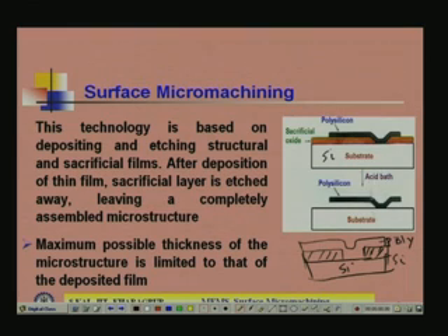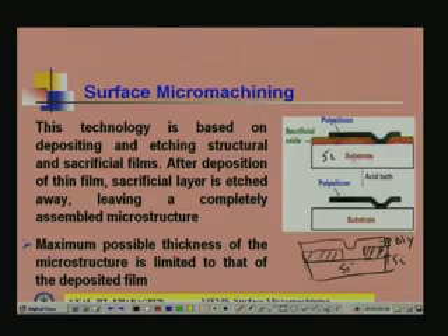Now, put the whole thing in an acid bath which can etch the sacrificial oxide. You see, oxide is not a crystal, so that etching is isotropic etching. It is not direction dependent like silicon etching, with 1 1 1, 1 0 0 or 1 1 0, where the anisotropy of etching depends on the crystallographic plane orientation. Those points are not coming into the picture in this particular case, because you are etching silicon dioxide, whose etching solution is buffered hydrofluoric acid. So, if you etch the sacrificial oxide, that is basically isotropic etching.